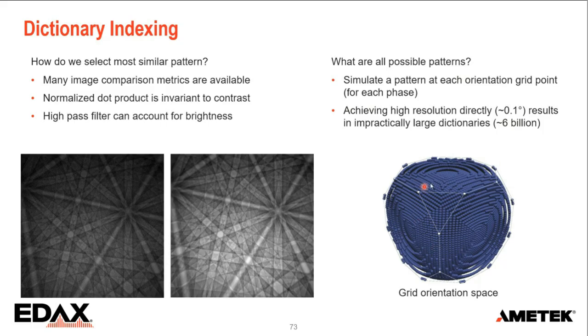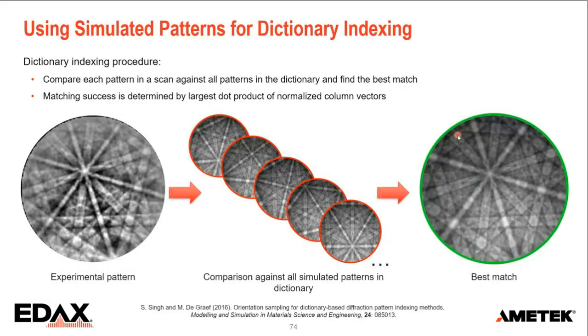So you have to subdivide orientation space into specific units. We do that, and we make a library with a sufficiently large interval between orientations that it's still manageable, and then we try to match the experimental pattern against all the possibilities until we find the best one.